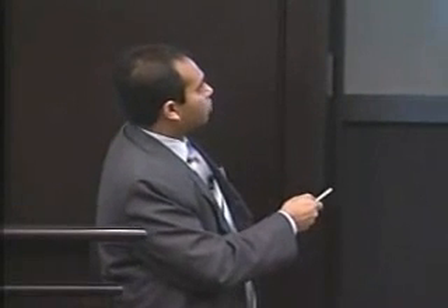At a lower rate, which is C/25, at almost 25 hours of discharge, the capacity has a full utilization. But the interesting thing is, even at a 1 hour discharge, we had almost more than 85% discharge capacity of the starting material. On top of it, if you do the cyclability of this material, as you can see, the material doesn't lose any of its capacity. It's pretty flat.